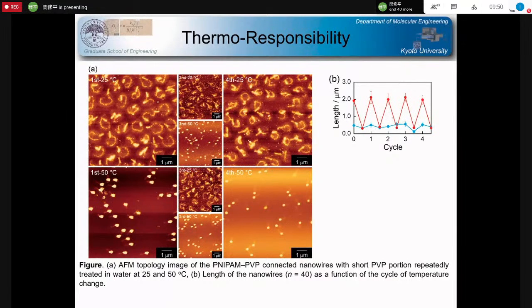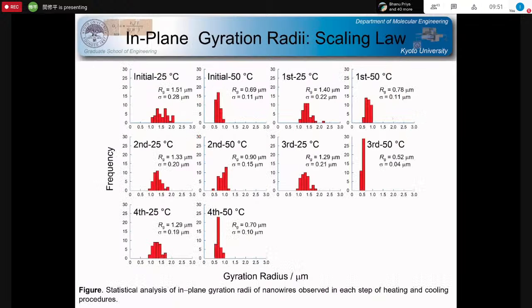One of the critical issues in the case of responsive nanomaterials is their reliability against external stimuli. So we also checked the thermal responsivity against temperature for one segment of the nanowires. As shown in this viewgraph, the stretching and shrinking of one segment of the nanowires can be confirmed again and again. Very high reliability for the morphological changes can be confirmed by these very simple experimental protocols.